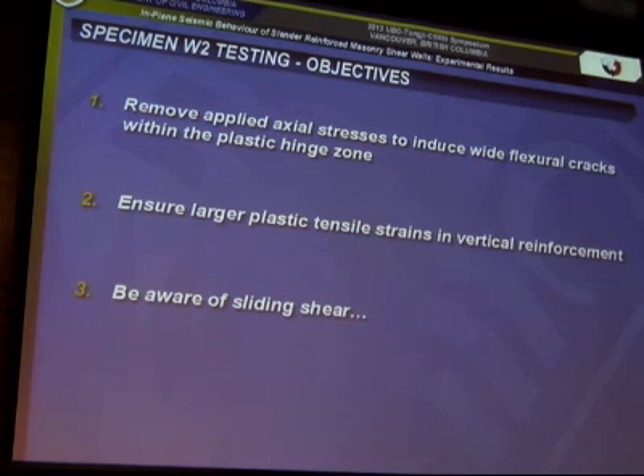So looking at the objectives for the second test, based on these findings, we had to remove the axial stresses to create those uniform wide flexural cracks over the height, and in turn also increase the large plastic tensile strains in the reinforcement. And of course, because we're reducing the axial load, we had to now be aware of sliding shear at the base. So looking at the loading protocol for the second test, it was quite similar to the first test. In fact, identical initially, except the much greater ductilities caused us to keep on going for quite a long time. And with this test, there was no axial load.